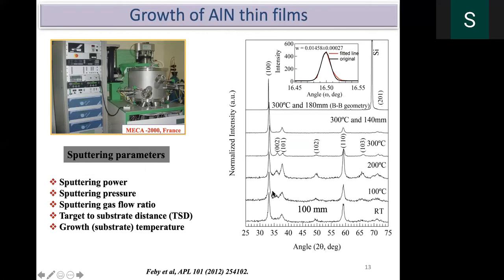You can understand from this aluminum nitride, the target to substrate distance is 100 mm, and from that, if I grow, one particular orientation grows, others are suppressed when the temperature is increased from room temperature to 100, 200, and 300. When I change the target to substrate distance suddenly from 100 mm to 180 mm, one particular growth is possible, that is 100, which I will explain. These are the possibilities. When you change the parameters, you can get wonderful